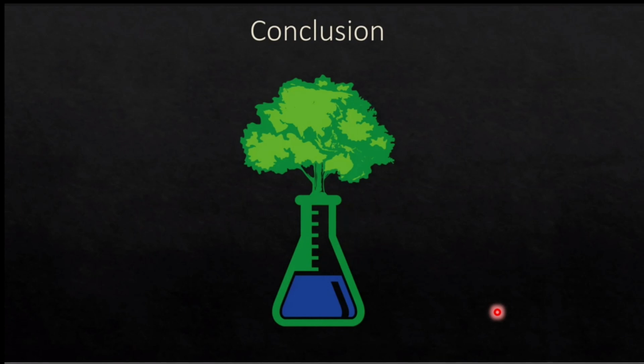Interesting. Do you see any limitations on the accelerated aging synthesis methods? Oh, certainly. It's not a fix-all. Who knows how far it could go? That needs to be determined by future research. But my first instinct is with porous structures. This has been noted in mechanochemistry, and I'm sure it will be the case once we get more into depth with accelerated aging, that the pore size is quite small with these compounds when they're made through these kinds of solid state synthesis methods.